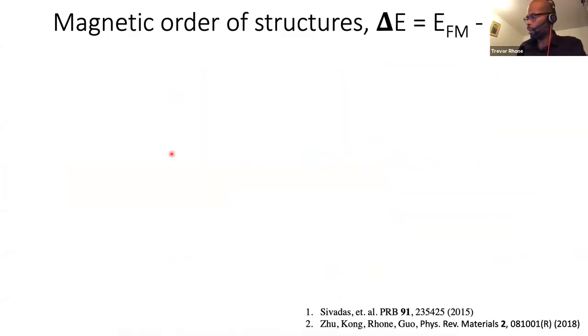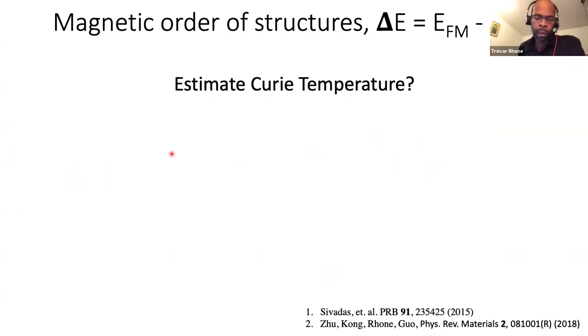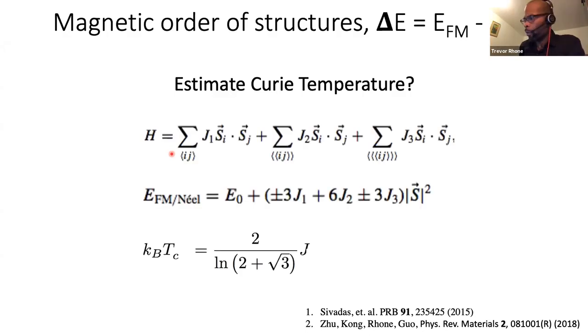Another thing we could do with these DFT energies, other than try to make quantitative predictions, is to estimate the Curie temperature. And one thing I'm leaving out of this estimate is anisotropy, which actually is quite important for predicting Curie temperature. But this is still roughly an estimate for the Curie temperature. And so you take the Heisenberg Hamiltonian, and you extract the DFT energy for the ferromagnetic states and the anti-ferromagnetic states. And using these formulas, you can have an estimate for the Curie temperature.